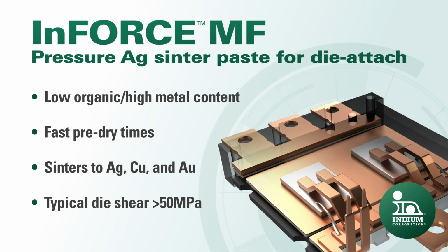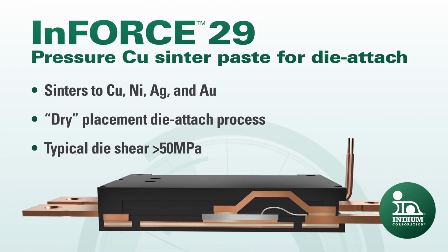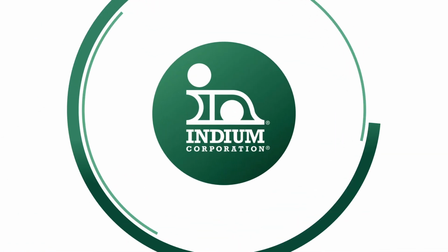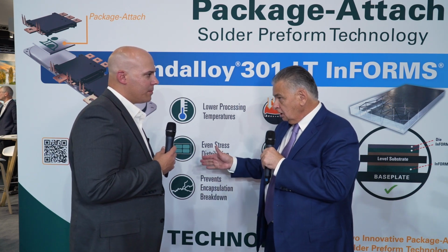So we have different formulations, some designed for where pressure needs to be applied, pressure sintering, some that require just reduced pressure or even no pressure with an extended temperature profile. The advantage of that is it provides options that can address the different manufacturing concepts that our customers see. And the other advantage of copper is you have a little more flexibility in the overall assembly materials, with the metallization choices for the die or the substrate. And again, it helps with the cost of ownership. We see that as a critical need, so we are advancing our copper sintering materials along with our silver sintering materials. So what are the trade-offs when you're using a non-pressured sintering process?